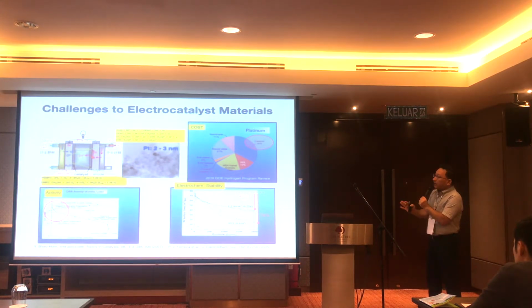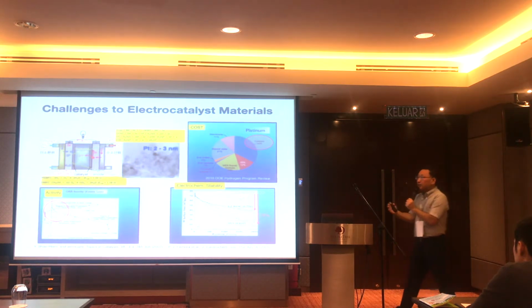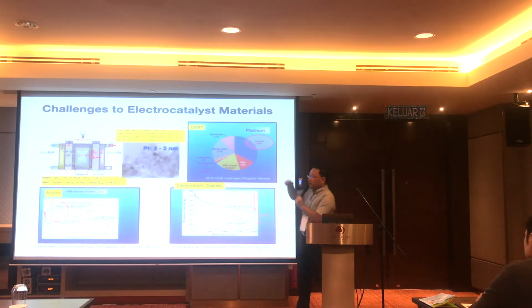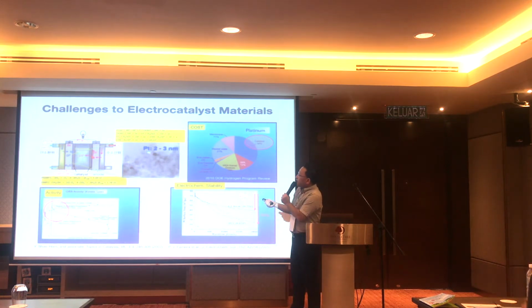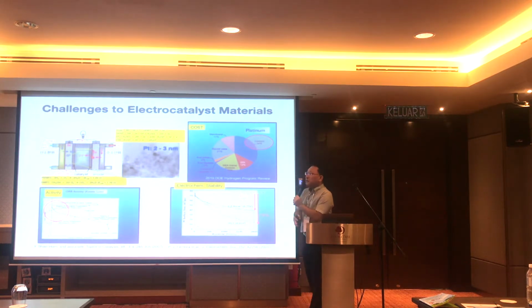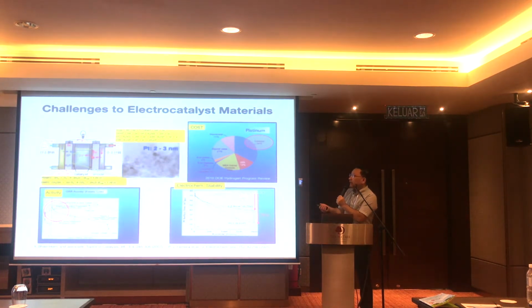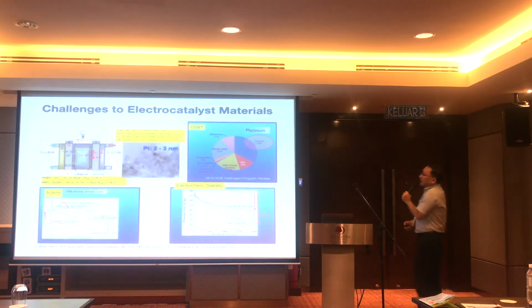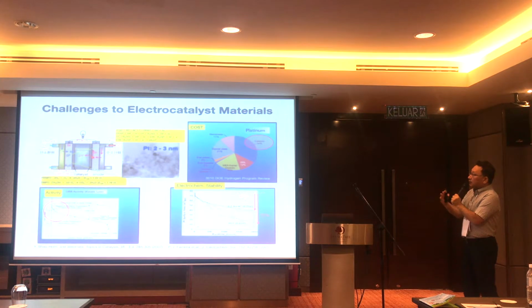This reaction should be thermodynamically spontaneous, but in practice, never. So we need a very good catalyst material to reduce the activation barrier. So far, what we found is that platinum is the best material, only at this size regime. If you find a material better than platinum particles, I'm definitely sure you can get the Nobel Prize. So at this size, only platinum.